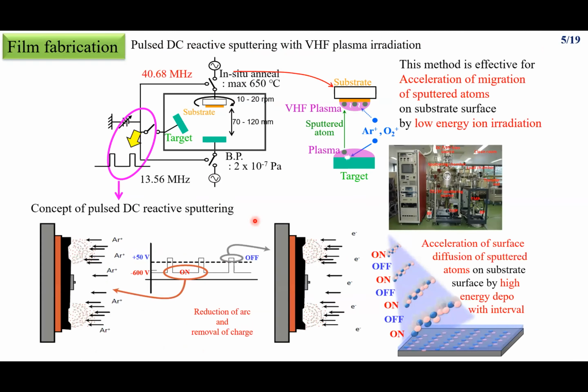So we fabricate our thin films by using pulse DC reactive sputtering with very high frequency plasma irradiation. This is similar to all sputtering machines, so I'm not going much into the sputtering part. Only one thing I will say here: we use VHF plasma, which really enhances the crystallization of the thin film, thereby enhancing the magnetic property.